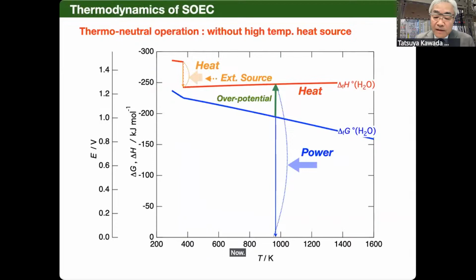No. In low temperature fuel cells, very pure hydrogen is necessary because a small amount of carbon monoxide will affect the catalytic property of platinum. But in high temperature systems, CO can be used as the fuel itself. So you do not have to clean up CO. But if you have sulfur containing gases, that is harmful for the fuel electrode. So you need to use some chemical filter before supplying the fuel to the fuel cell.